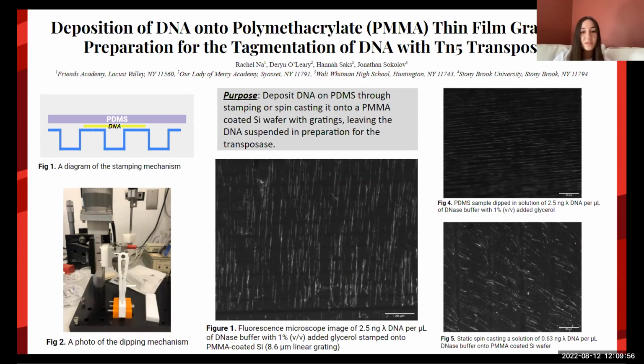We used two methods to deposit DNA onto gratings. The first method we used was stamping DNA onto silicon gratings, which is shown in figure 1. First, we placed a piece of PDMS that was dipped into solutions with different concentrations of lambda DNA in either DNase or TE buffer, with varying concentrations of sodium chloride to promote adhesion to the PDMS. Instead of sodium chloride, we also tried using a 1% concentration of glycerol to encourage the DNA to transfer from the PDMS to the silicon grating.